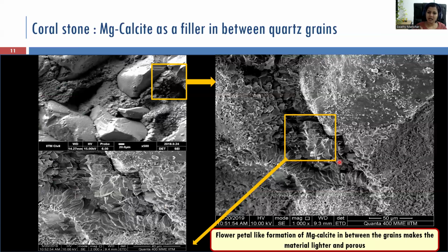Because of these larger pores in the system, when we subjected this particular stone to accelerated salt weathering, we saw that it had very high resistance to salt weathering. Now you know why: salt can easily go and get deposited in the larger pores, and there are not many smaller pores in the system. This would help in not having damages in the system.